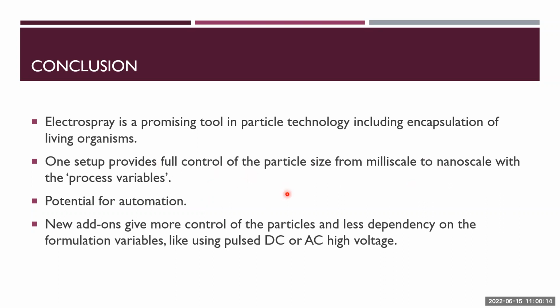And for me, one of the most important applications of the electrospray is the ability for automation. So we are working on optimizing the dripping using what we call on-demand drop, meaning that you control the number of drops precisely. Like you can control 1,000 drops per second. So if you get a suitable flow rate, or you control the flow rate, you calculate, you will get a suitable size exactly as you control.